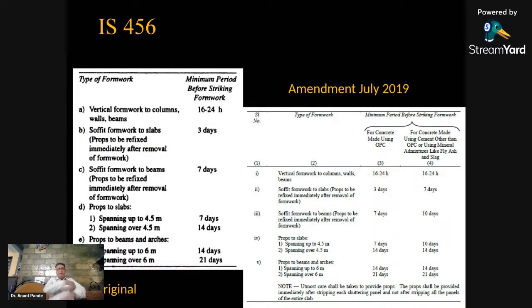Now IS 456, that most of you are following, just look at the soffit formwork to beams, minimum period before striking formwork. It was mentioned 7 days. Now the amendment has come: if you use OPC, then you can strike it in 7 days. And for concrete made using cement other than OPC, or using mineral admixture like fly ash and slag, you can strike the formwork in 10 days.